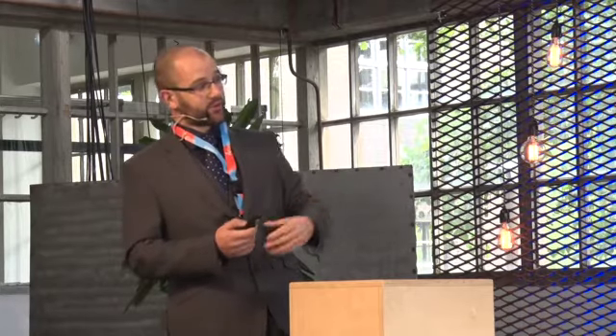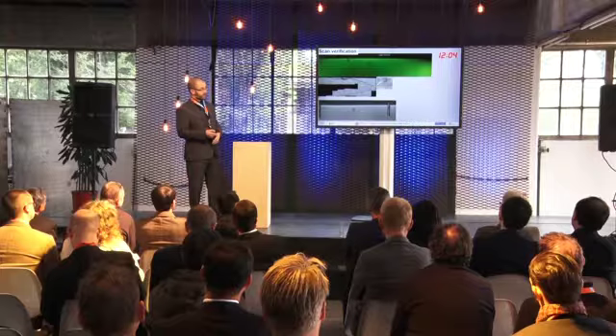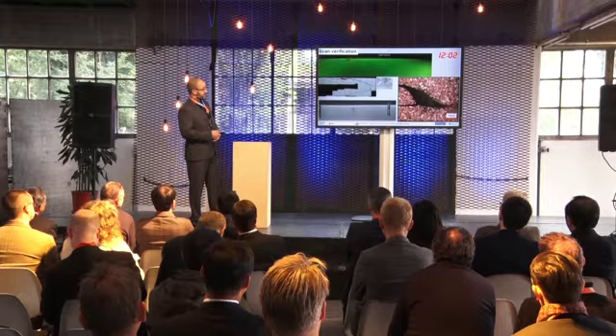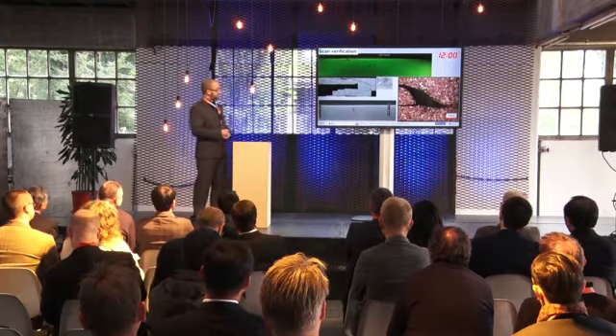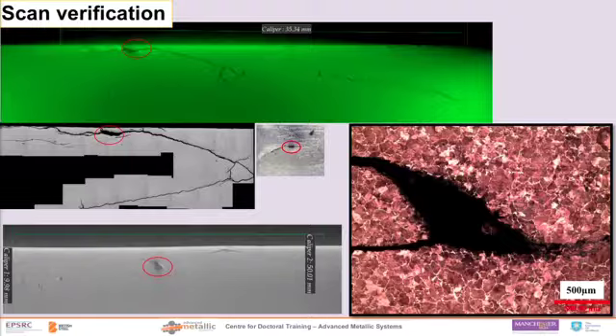So what about this one? We've got a very large shadow in the middle. This could be streaking. This could be a scattering effect due to the fact there's two cracks very close to each other, and this is what I assumed. Unfortunately, it is real. This is in the rail. I haven't run XRD on it yet, but I will be running XRD to find out what elements are actually inside there. And I believe this is very close to where the initiation took place.